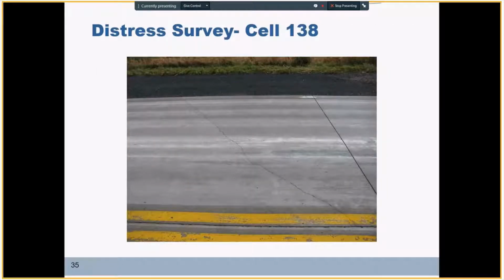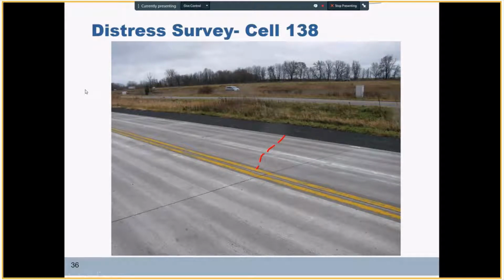We also have one diagonal crack formed in cell 138. It seems there may be some problem with the base, with cracking under load here. I wouldn't consider this crack related to the concrete material properties - it would be some sort of structural crack, but we can discuss it later if you have comments. This is another view of that crack, starting close to the intersection of the joints, propagating at about 30-35 degrees in a diagonal direction through the slab.